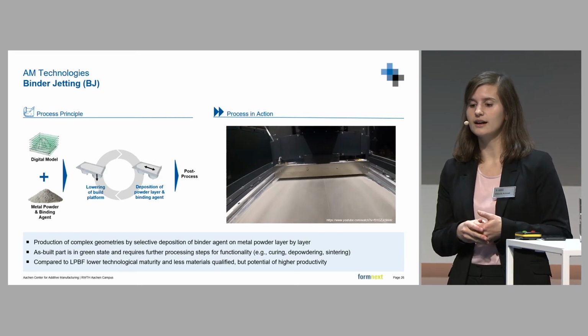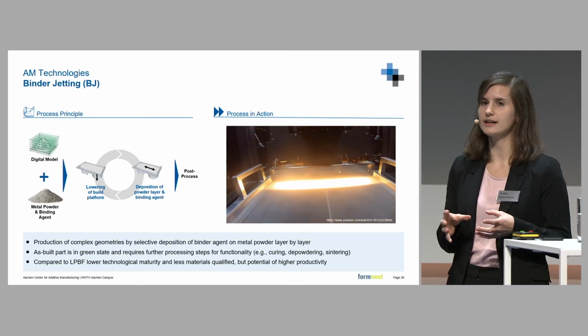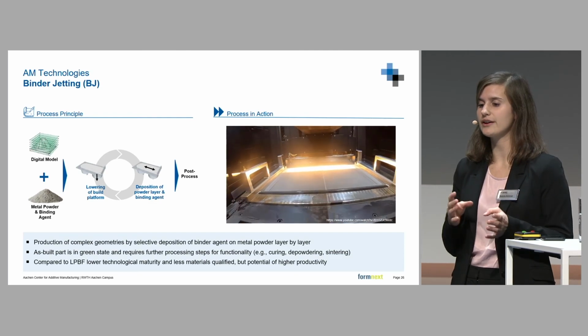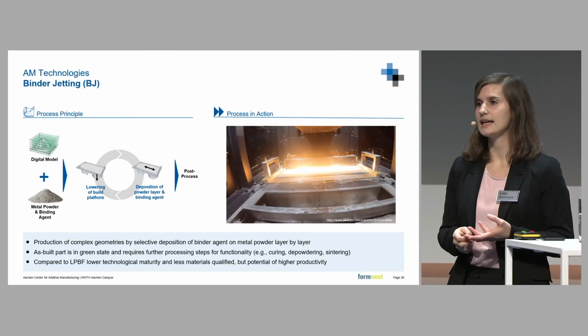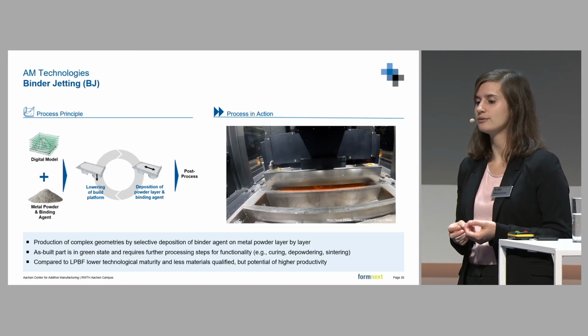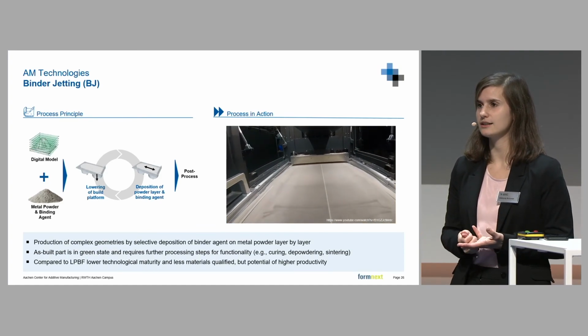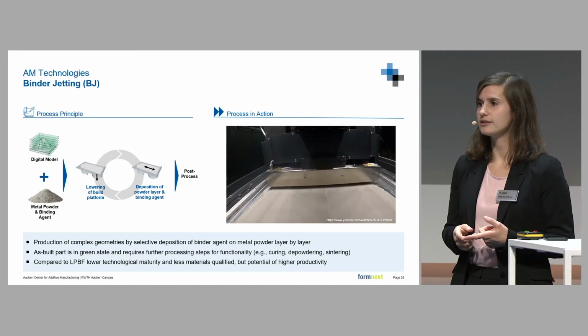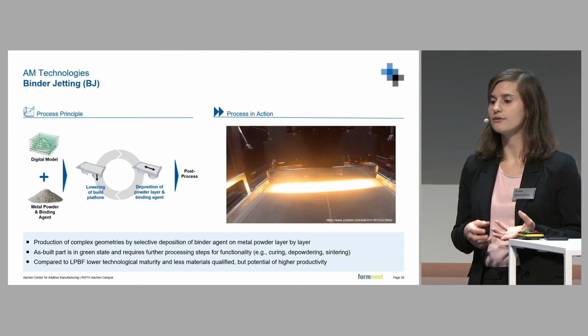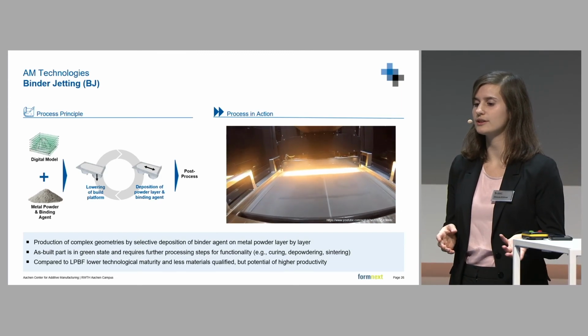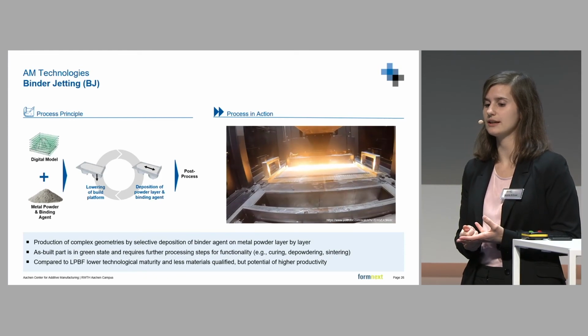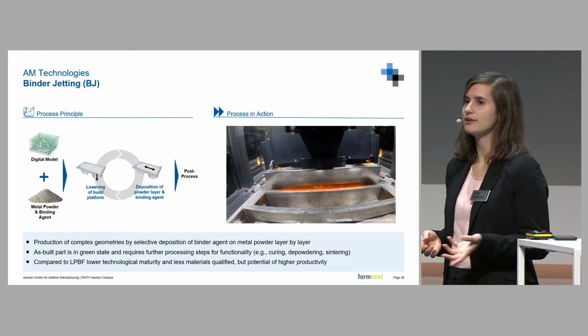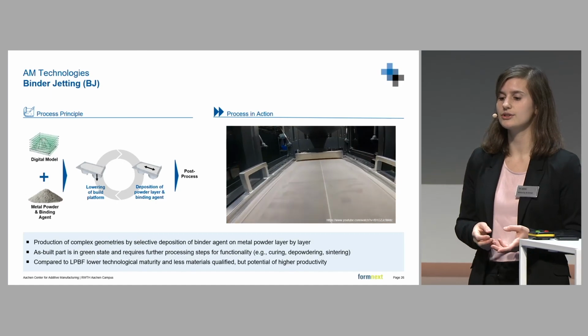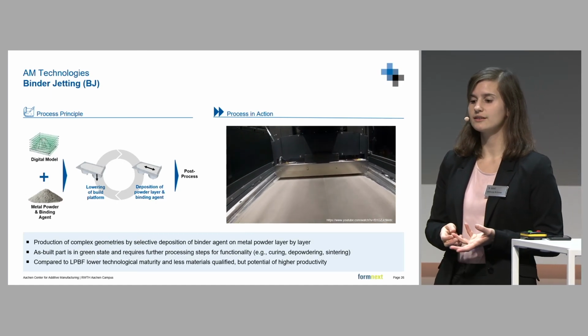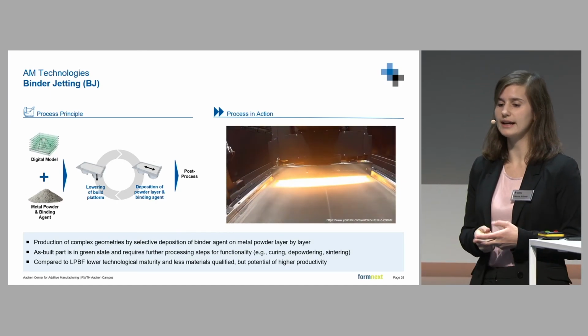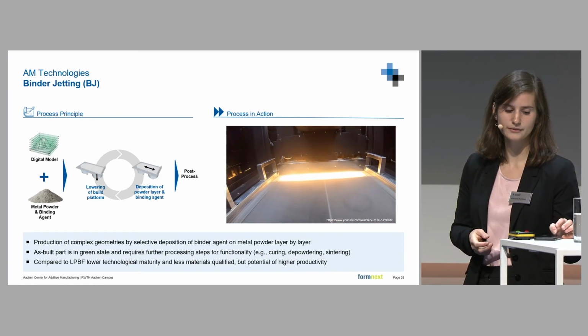Downsides of the process are that when you have the parts, they are in a green state and very fragile, so you need to perform very extensive post-processing in order to give them their original functionality. For example, curing, depowdering, and sintering to make sure the parts are no longer fragile and that you can actually use them for the use case you intended. So compared with LPBF, binder jetting has lower technology maturity and fewer materials qualified, but it has the potential of higher productivity compared with laser powder bed fusion.